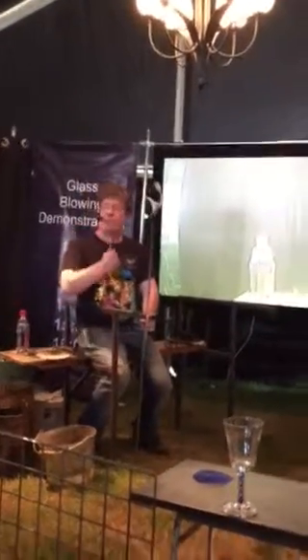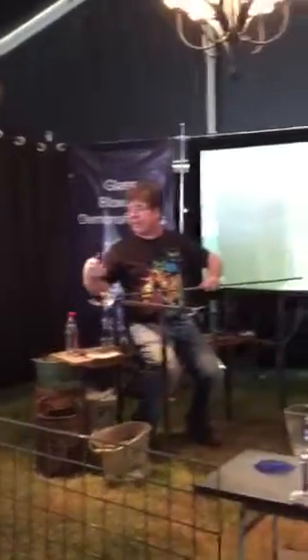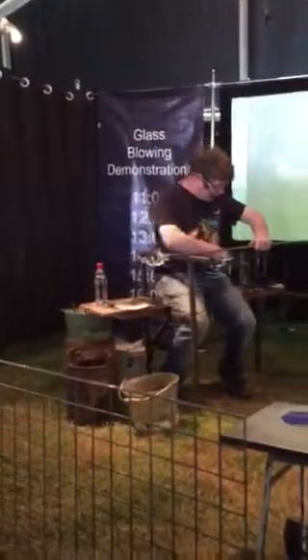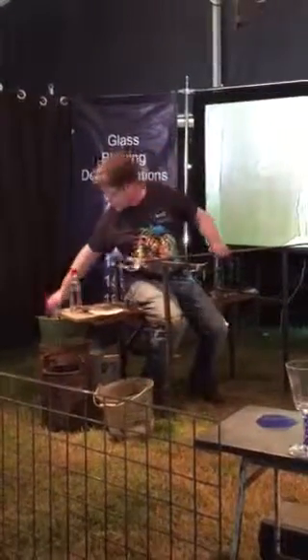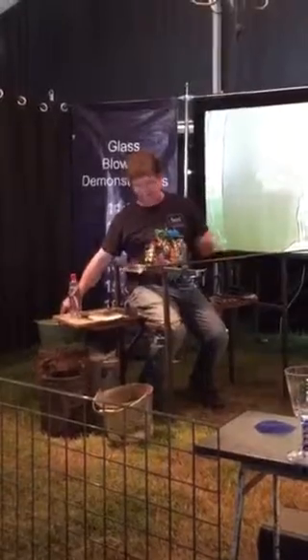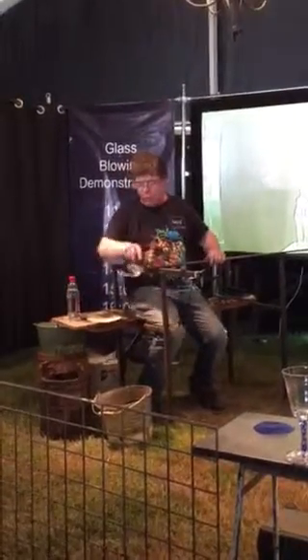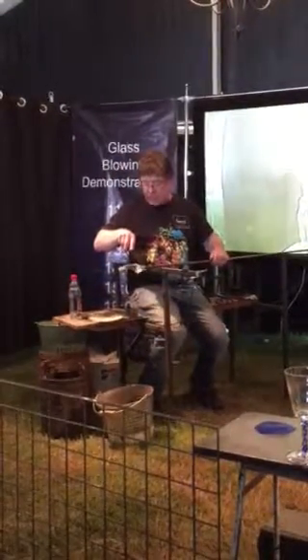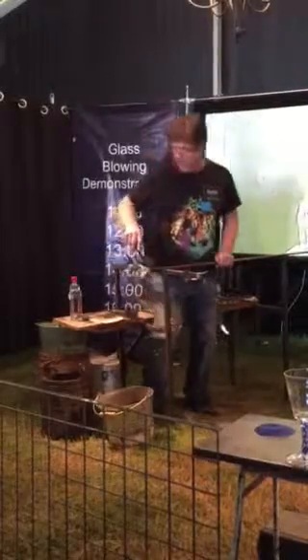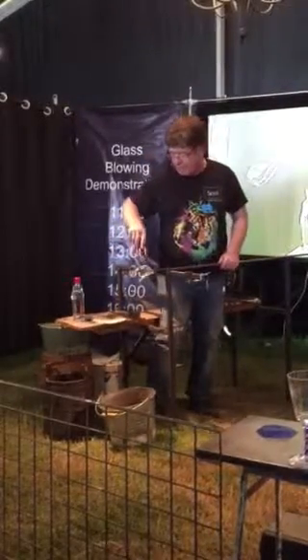So to stop that, what we need to do is take it off this line and put it into a second oven, which is held at 470 degrees, evens out the temperature, and then cool it down very slowly from there. So what I'm going to do to get it off here, because it's still about 600 degrees, is put some cold water onto the base. So what that's doing is putting a big thermal shock into the glass. Very, very fragile on the base there.